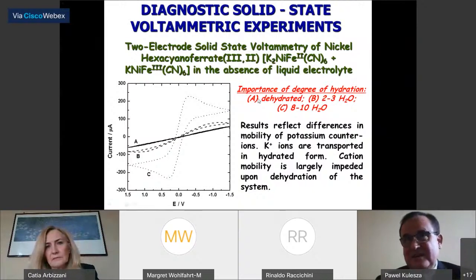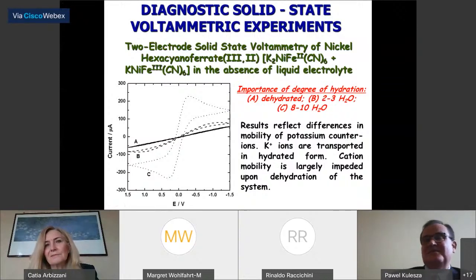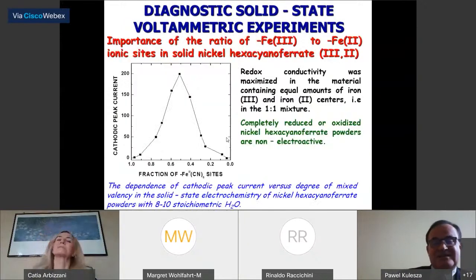I remember with nice weather in Camerino during the old days, it's also nice now in summer, the system could evaporate very fast and go from the nice reversible peak to a straight line. So it was very interesting. 50-50 iron 3 to iron 2 gives you very high current, maximized currents.